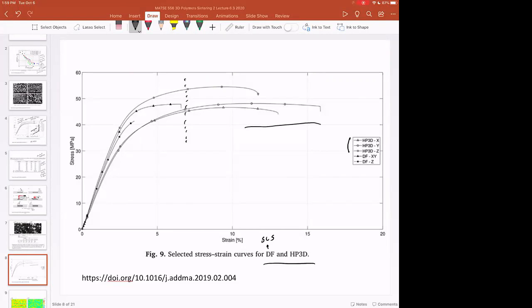these types of studies really depend. How good are they at SLS? Are they using the latest techniques? Are they trying to focus on HP processes? Is this really a group that's experienced in high-speed sintering? And so you oftentimes have to look at this type of data with a skeptical eye, because the question you might ask yourself is, are they using the best SLS conditions? But based on everything else that we've seen, elongations to break or strains to break of 5% aren't unreasonable for SLS. It's just that they're getting pretty good performance from their HP process in regards to elongation to break. And so that's just an interesting observation.